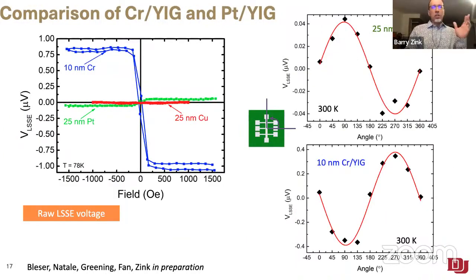So here's what happens. This is, again, the raw voltage that comes out of these experiments now. And you can see in blue, we've got the case for the 10 nanometer thick chromium, again, in this sort of high spin conversion region. And we get really pretty significant signals out of this. And again, this is in microvolts here, but that has everything to do with the actual size and how much current we applied, what the actual thermal gradient is here. These are all the same currents for the different materials in this one plot. We'll get it all properly normalized in just a second. But it's nice that we get a nice, big, easily measurable signal out of the chromium.